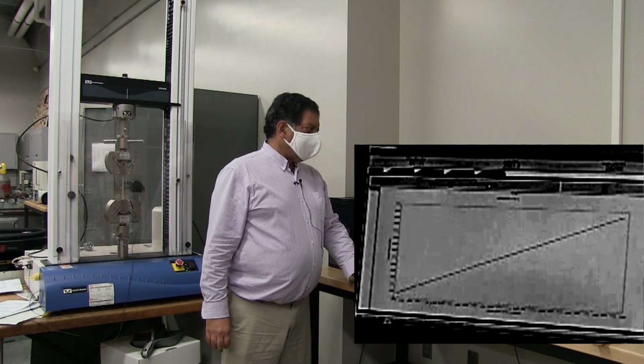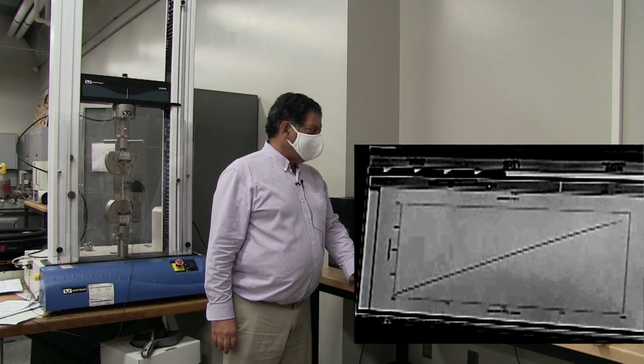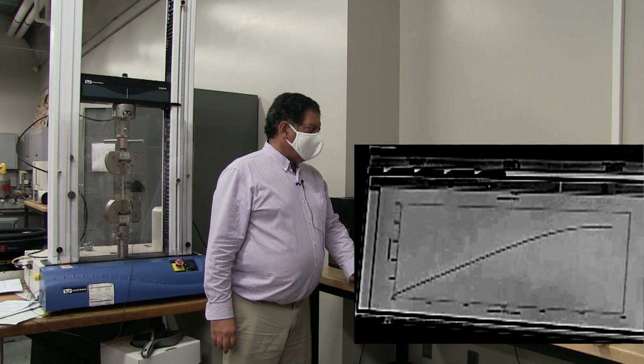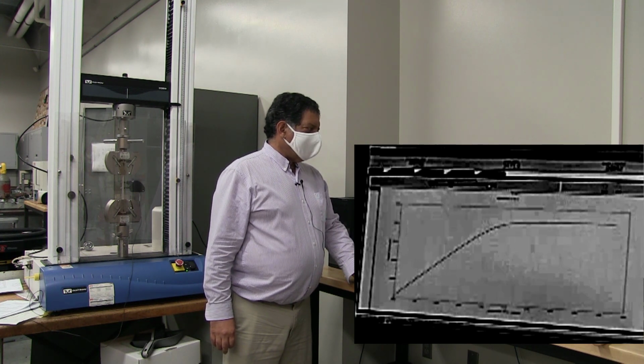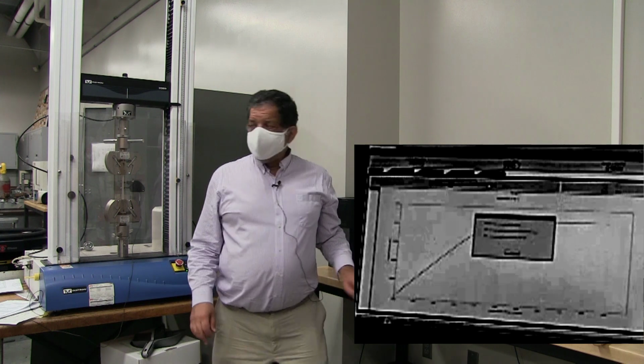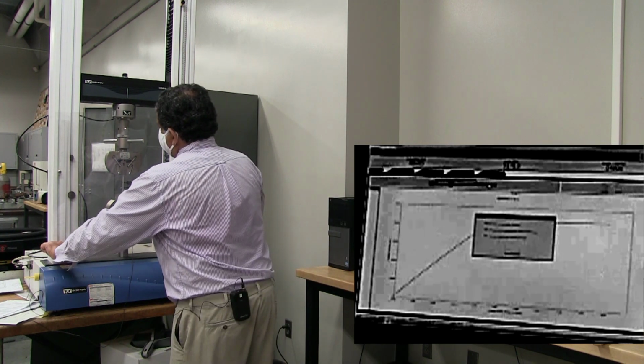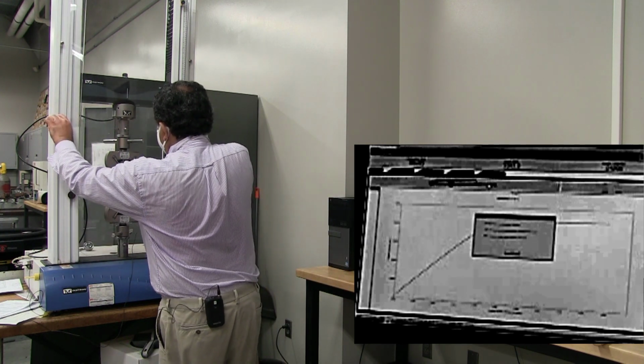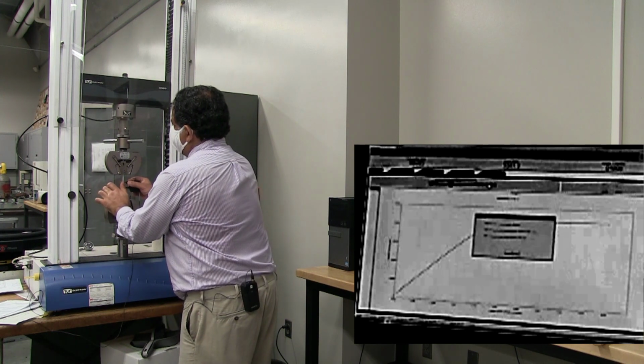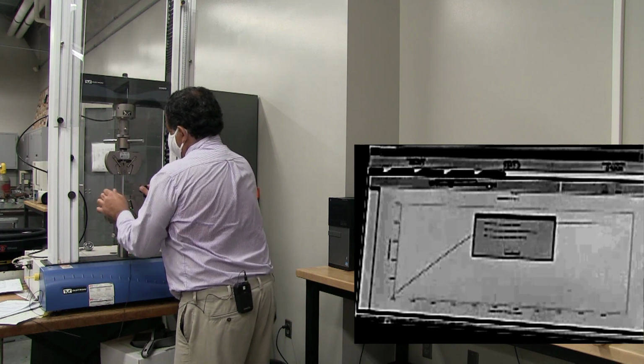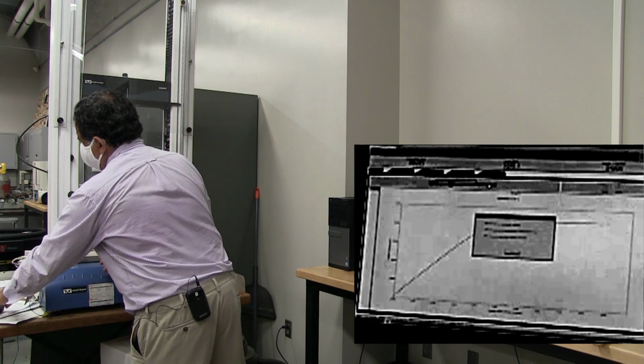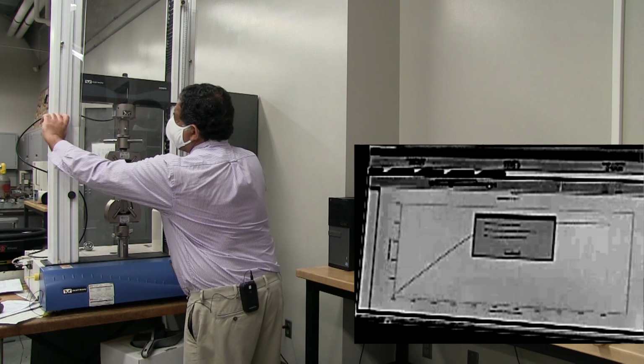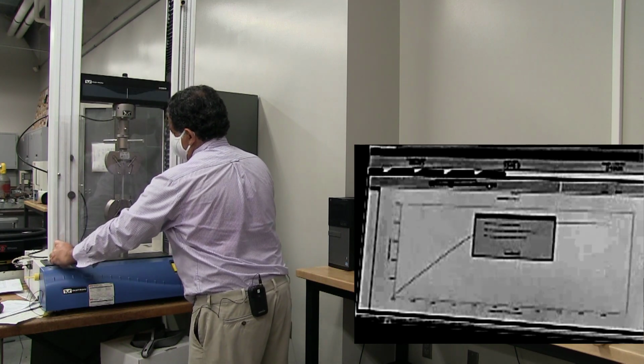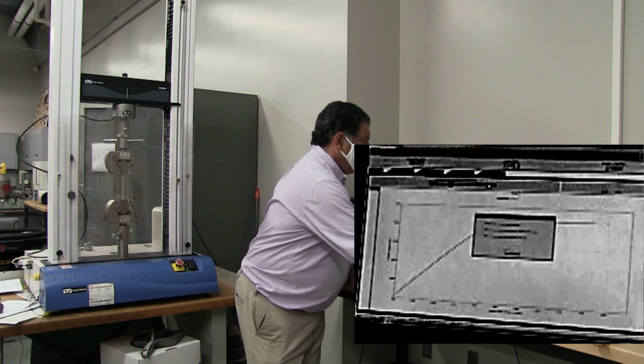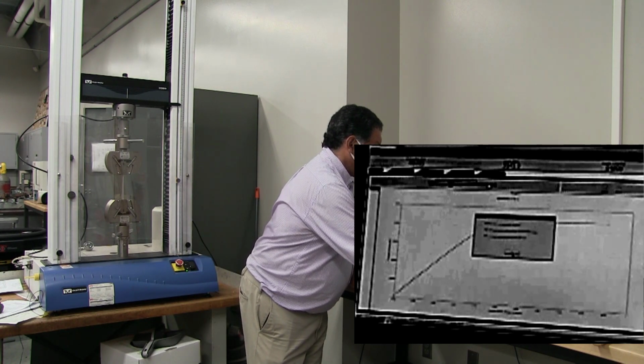So there's the elastic portion of the test. And it yielded at 3,000 pounds instead of closer to 6,000 pounds. So that's the low strain portion of it. We have enough information to calculate yield and elastic modulus. So I'm going to remove the extensometer and then run for the rest of the test.